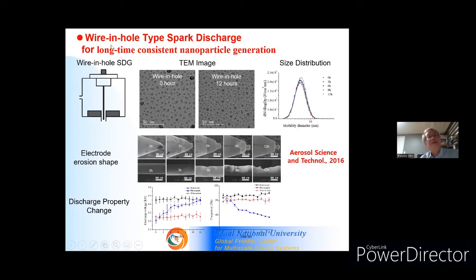So we developed a new type of wire-in-hole spark discharge, using a thin wire and cylindrical hole. In this case, we found the size distribution is relatively similar even after 12 hours, and at the same time we can generate unagglomerated nanoparticles. The electrode erosion shape in the tip and pin-to-plate type changes the size distribution after long deposition occurs, but in our wire-in-hole type we obtain relatively uniform size distribution.